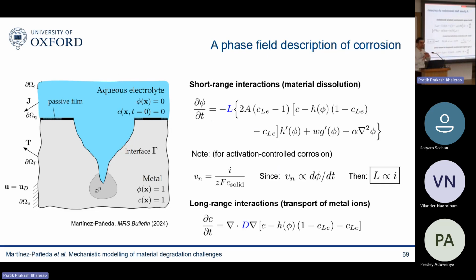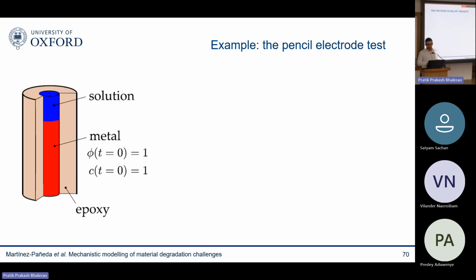So basically, the simplest model you can think of, there's many other things, there's mechanics, but for the time being, the simplest model you can think of has two equations. One for the short range interaction, so material dissolution, atoms being detached from the metal, so to say. That is captured with the phase field model, the Allen-Cahn type of equation. And basically the parameter that matters is the L, the mobility coefficient, and we have shown that that mobility coefficient is proportional to the corrosion current density. So again, a parameter that you know before you run your calculation. And then the other equation is a transport equation, a Fick's law type, where you capture the transport of those metallic ions, the long range interactions, that relies mostly on the diffusivity, which is again a material property that we can measure independently. And let me show you how it works.